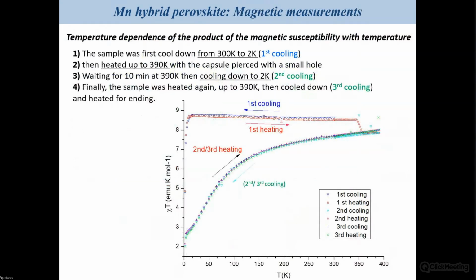If you look at what happens when you check the magnetic behavior of that system, you see that again the magnetic behavior you observed for the first cooling is completely different to the one you observed for the second cooling. It means that, from the magnetic point of view, you have very different behavior after the first heating. And this is, again, the sign of a transition happening at the first heating.